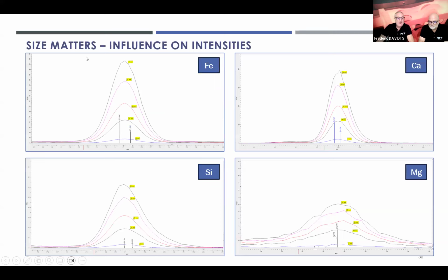So we can see here now different elements: iron, calcium, silicon, magnesium again, so heavier elements and lighter elements. And we can see that for the 32 millimeters down to the 8 millimeter, we can see peaks for iron very clearly, also for calcium and silicon. Magnesium is already getting a bit more difficult. So here we can really see with an 8 millimeter mask, we have basically lost our peak. So again, we can see an influence on the size of our sample.